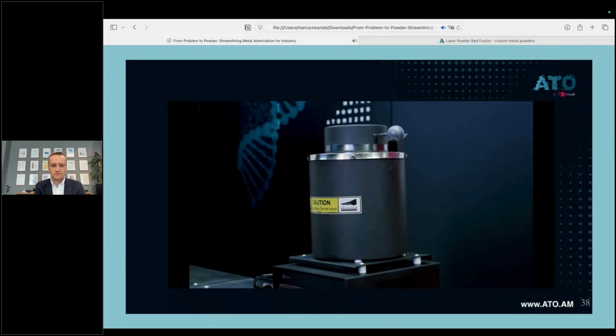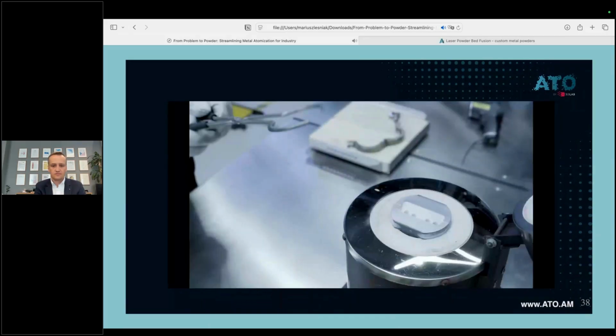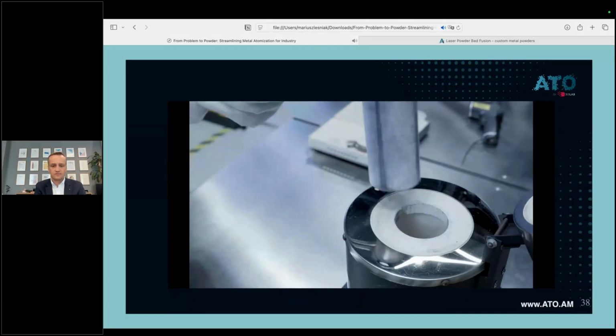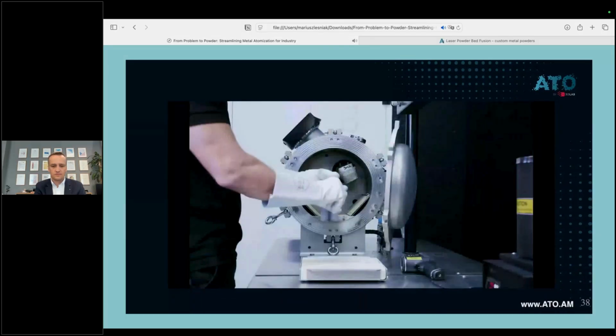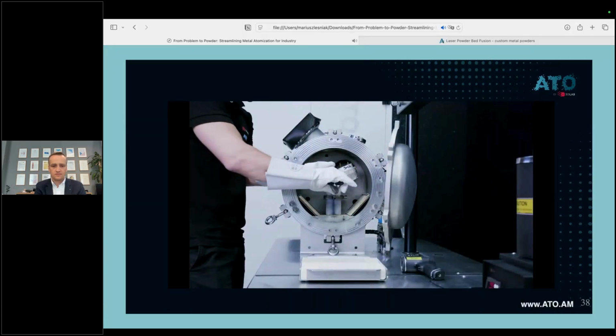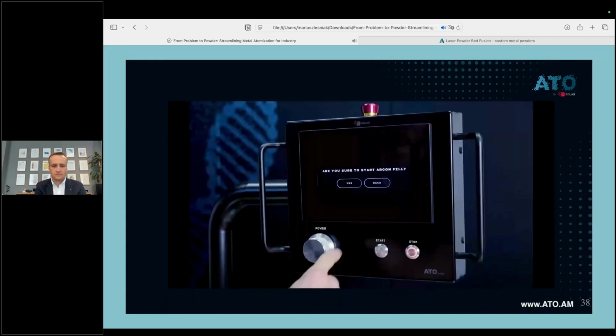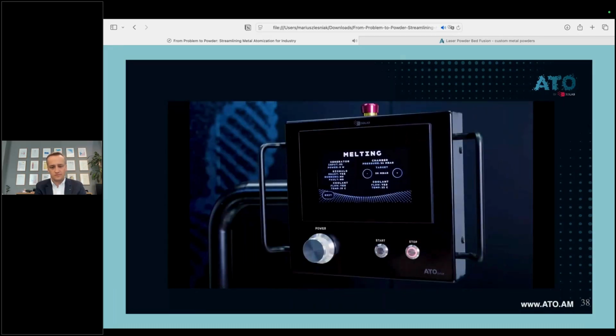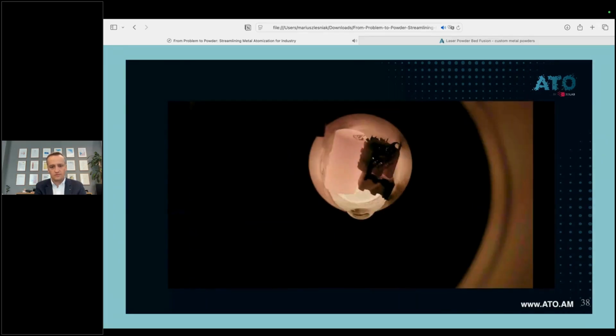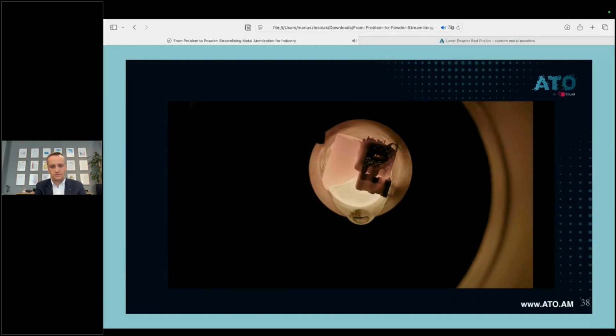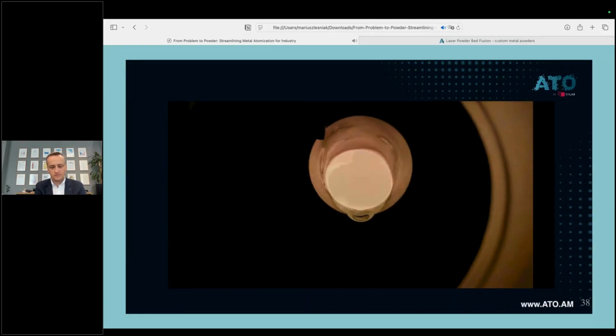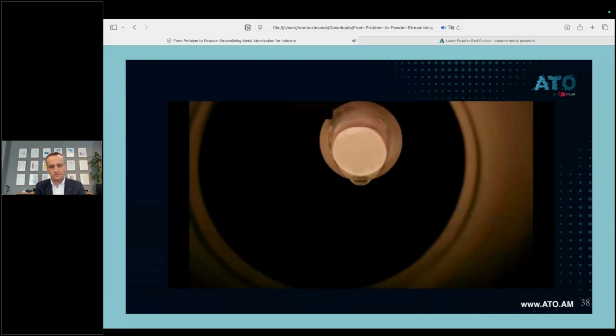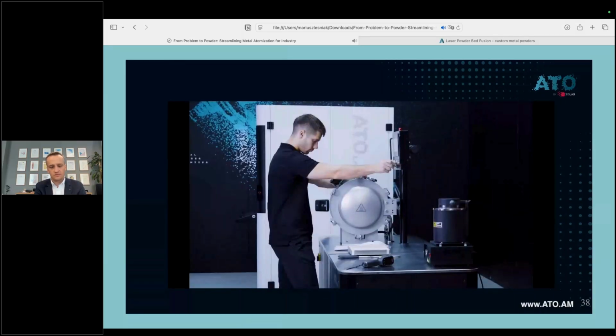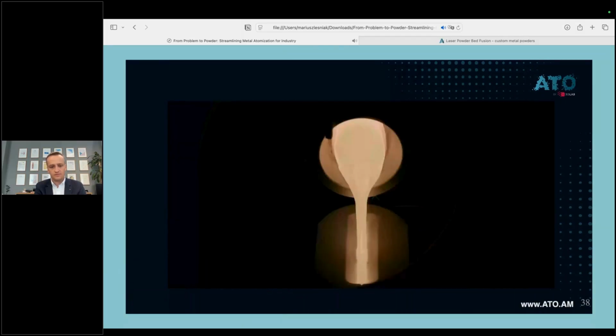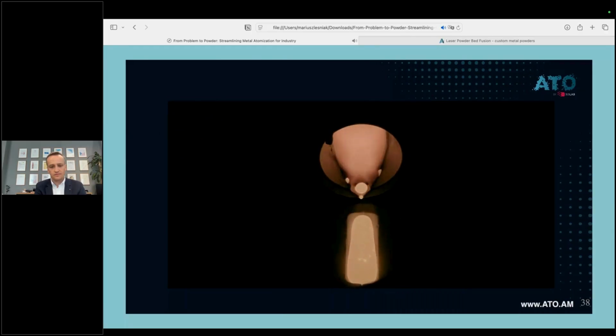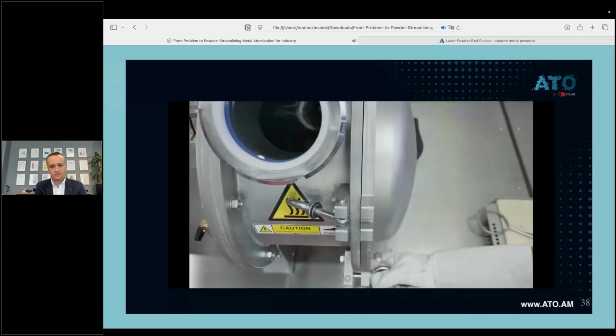Take and secure the mold with a metal clamp and position it directly under the crucible drop spot. The ATO Cast chamber works in positive or negative pressure version and with an inert gas shield to reach the highest material quality and purity. When all is sealed, start induction melting on the main touchscreen panel and watch how your feedstock becomes liquid. Material fully homogenizes with the induction electromagnetic field. Once the melt reaches its ideal state, pour it into the casting mold with a firm motion. Casting is now complete. The rods can be safely extracted and used as fresh feedstock for powder production.